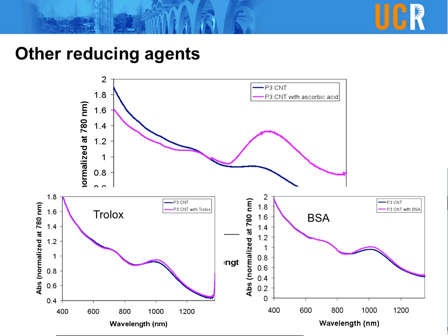However, once we add the Trolox to the solution, the oxidation of DCFH will stop right away. So we still haven't figured out why. And a similar phenomenon was also observed with BSA. So right now we still think Trolox may be absorbed onto the surface much more strongly than DCFH. So actually after the absorption, it will suppress the active site on the carbon nanotube surface, so the DCFH will no longer be oxidized. However, we still have not proved that point yet.